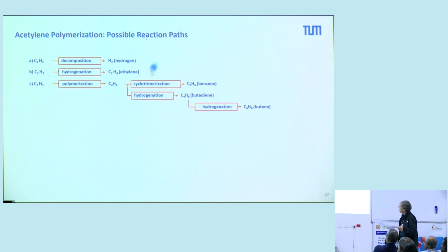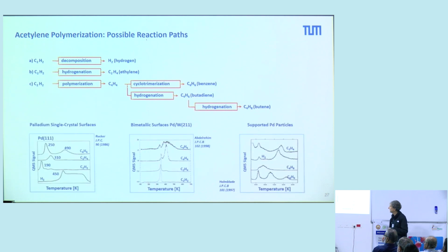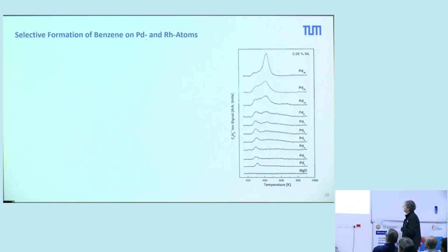If we combine 3 of these molecules to form benzene, this intermediate can again have a hydrogenation to produce butadiene, or we can have hydrogenation to produce butene. You see, this is a very complicated process. It has a lot of reaction paths that can take place. And indeed, this has been observed on single crystals, different materials, that you have a quite complicated product spectrum. But on clusters, you see that even a single palladium atom is active.